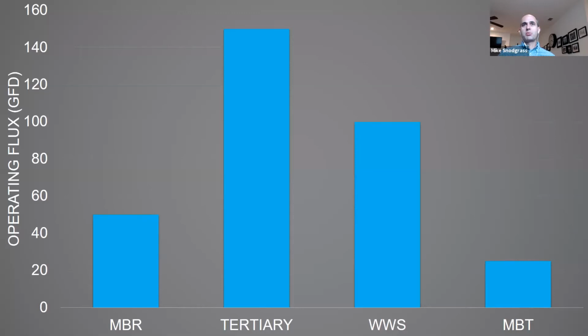These are some of the flux capabilities that we've observed in SiC on the different applications. On certain MBR applications, obviously it depends on how it's designed in terms of mixed liquor and temperature, but we've seen flux rates as high as 50 GFD on MBR. Tertiary up to 150 GFD. On wet weather systems, we're usually around 100 GFD. Then on sludge thickening, where you're usually over 3% solids, well over 20 GFD. So definitely significantly higher flux rates compared to what is traditionally seen.